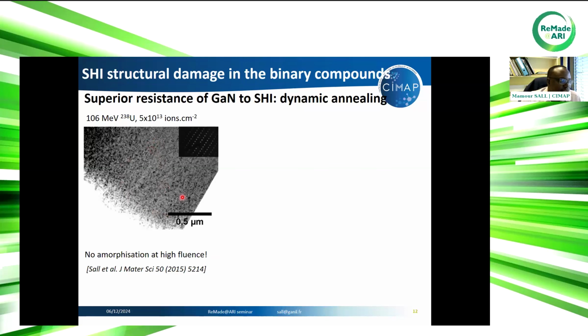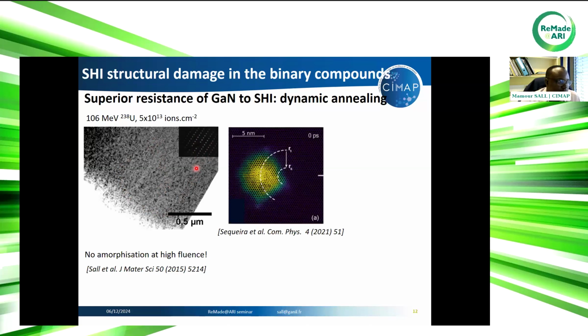From this TEM image and the diffraction pattern here, we can see that gallium nitride is still crystalline. At least the long range order is kept after irradiation. And this was again explained by using molecular dynamics simulation. For this, we started from one track created in the material. So this is a track created by one ion. And close to this track, we make another ion pass here.